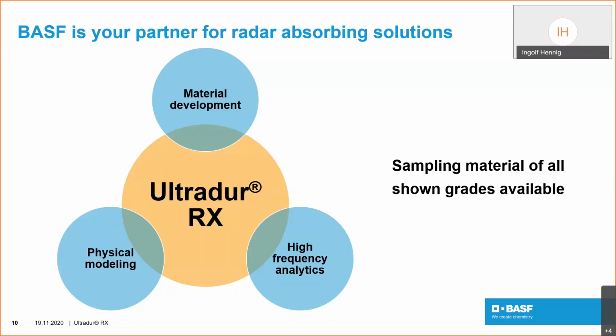So in our materials, the absorption is created by the dielectric loss. We have real dielectrics, so we have no conducting materials, because conductivity would increase the reflection. And the dielectric loss that determines the size of the absorption is created by a so-called interfacial polarization mechanism in our heterogeneous material. We have done studies of the absorption and of the dielectric parameters up to 120 degrees Celsius. And because this is a special interfacial polarization mechanism, nothing significant happens to the dielectric parameters up to this temperature range. That means they are more or less independent of the temperature up to this range. Yeah.